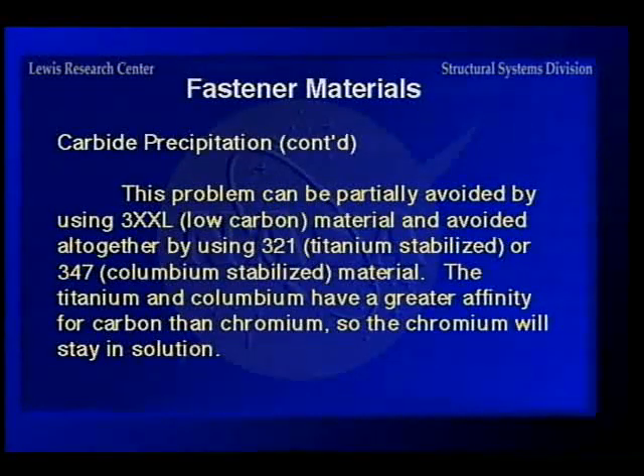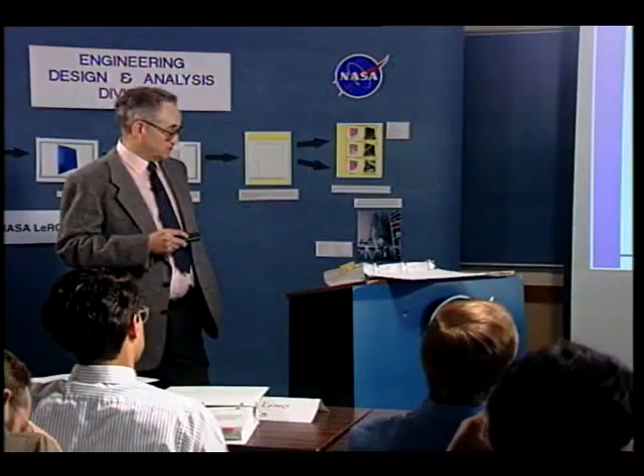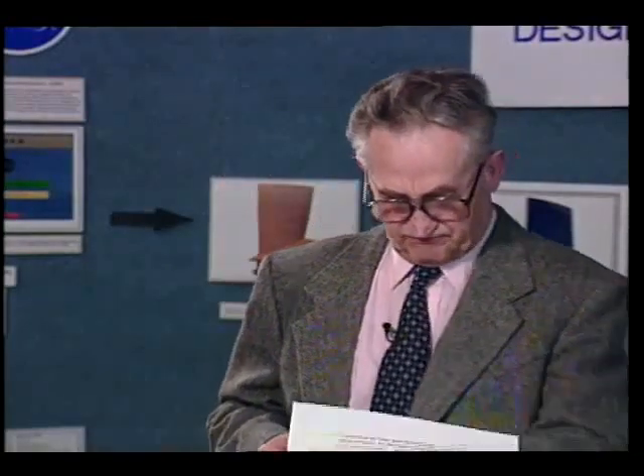So this is why, normally, if you're going to have welded joints, you try to use a 300 series with an L designation, which is low carbon, and even use a low carbon weld rod. Or better yet, and this is what we did at Martin Marietta on the Titan, you use 321 stainless because it has titanium in it. Or you can use 347, which has columbium. The titanium and columbium will combine with the carbon before the chromium will, so that'll leave the chromium in solution so that you still have the corrosion resistance. So keep that in mind when selecting fasteners for anything above about 800 degrees in the stainless steel, to use 321 or 347.